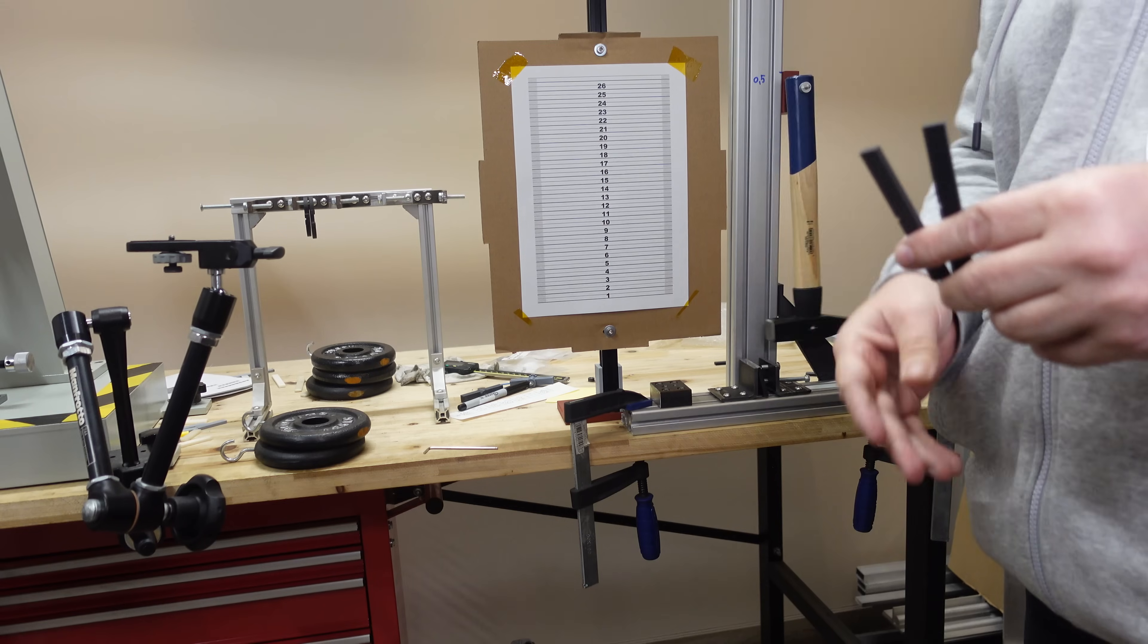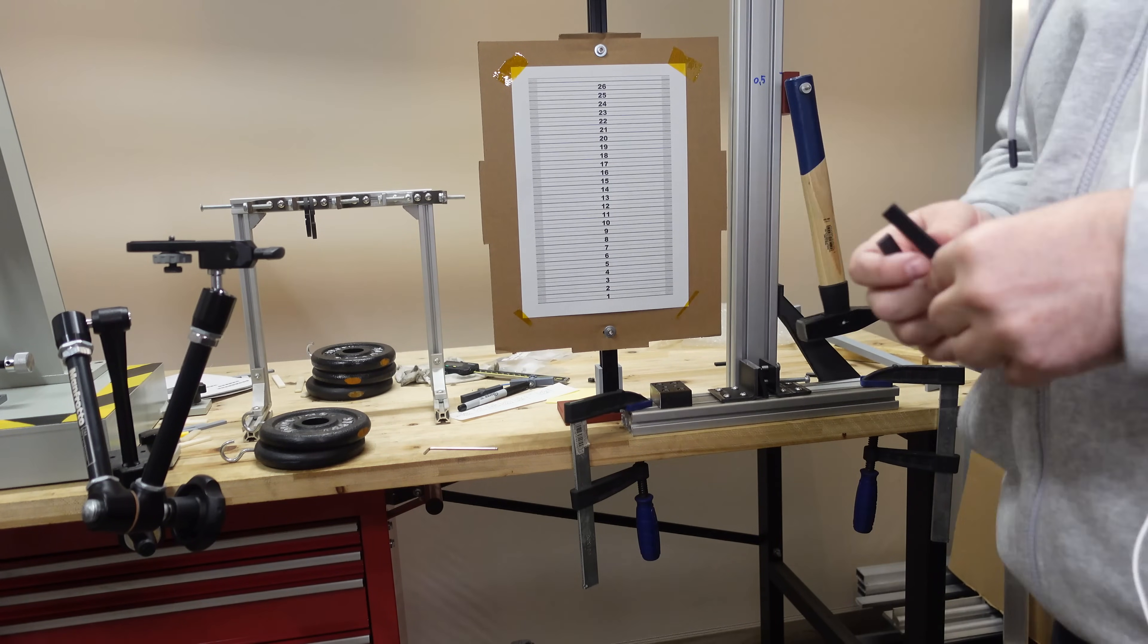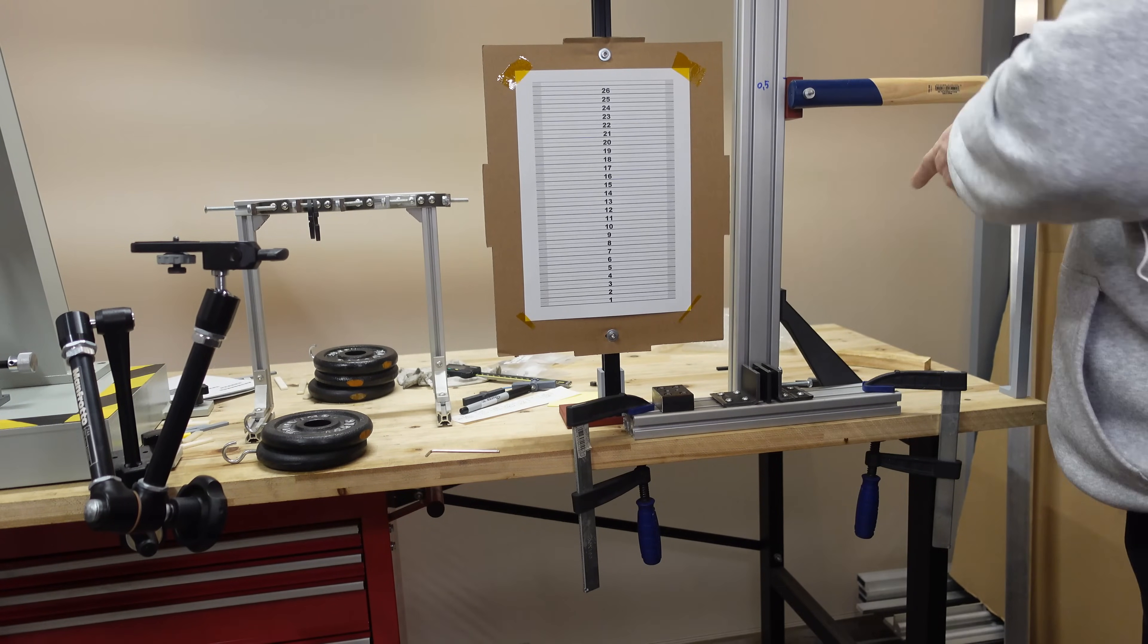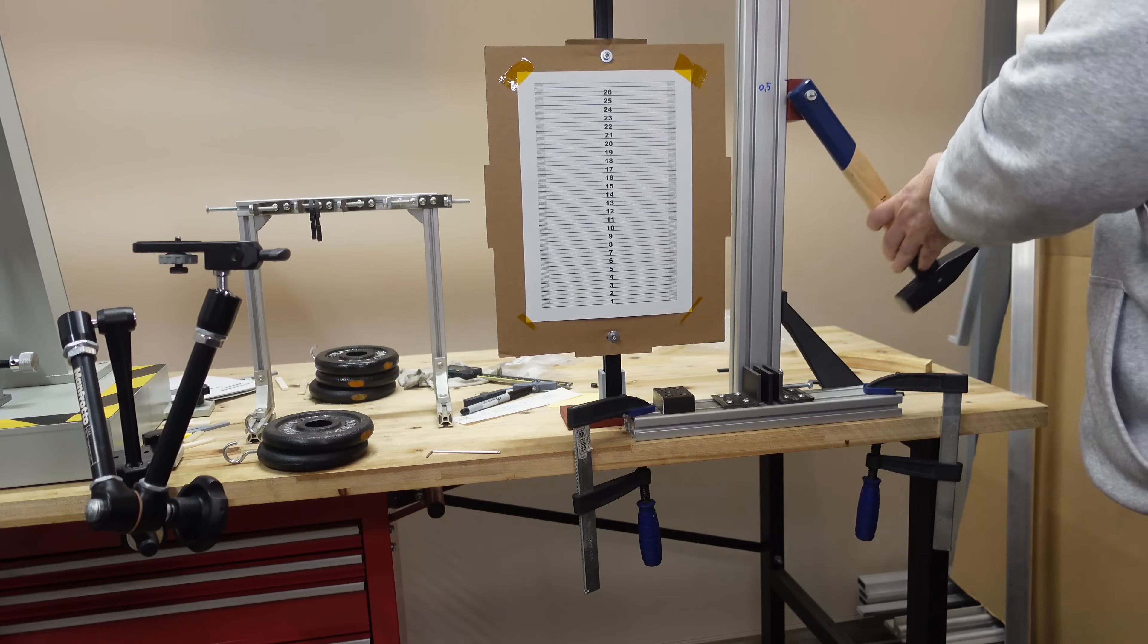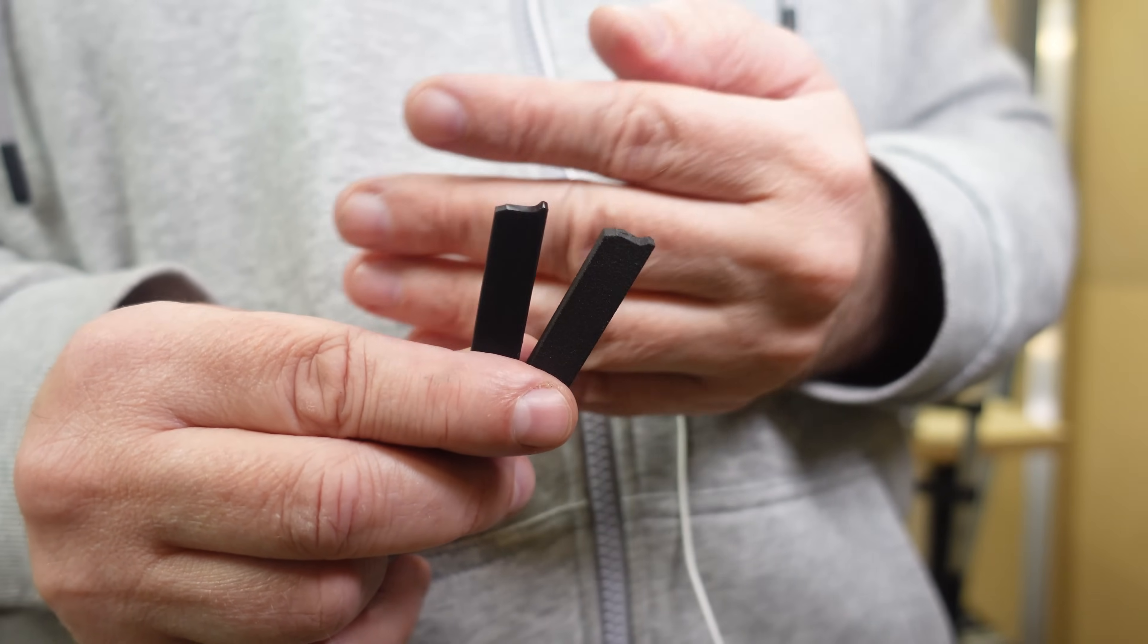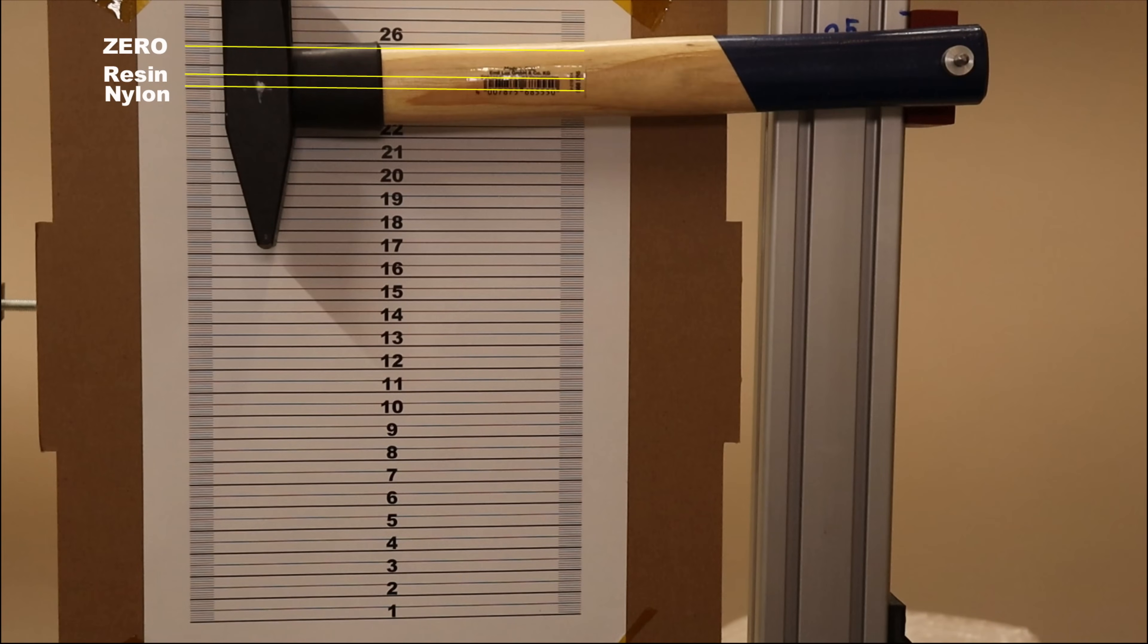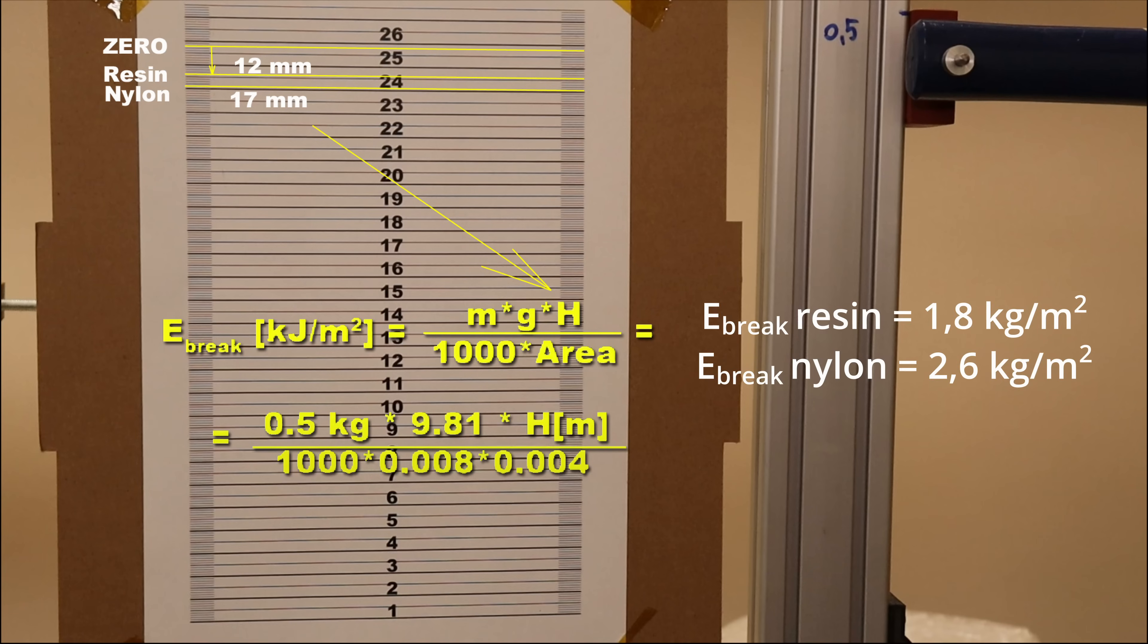And now the impact test with this half kilogram hammer and I believe that the nylon will have the advantage here but we will see soon. Resin. Zero position. Nylon. At this moment I'm not sure, the break looks very similar but let's analyze the footage. The zero position of the hammer and after breaking the resin test object and this is after breaking the nylon, and if I measure everything from the zero position I can get the edge which I can use in this equation. But this also means that the nylon is a slightly tougher material compared to this JLC black resin but in both cases these are quite brittle materials and here you can see the numbers in kilojoules per square meters.